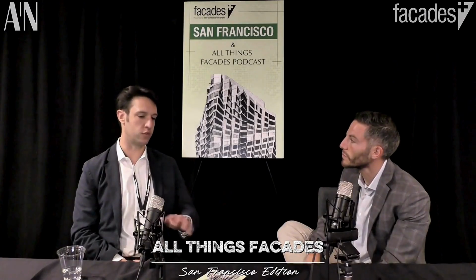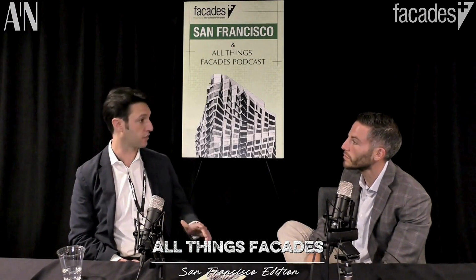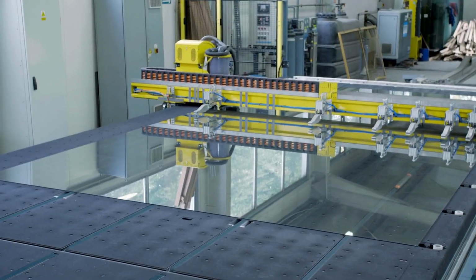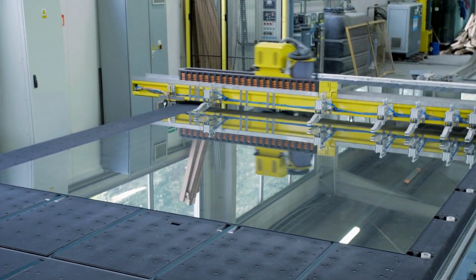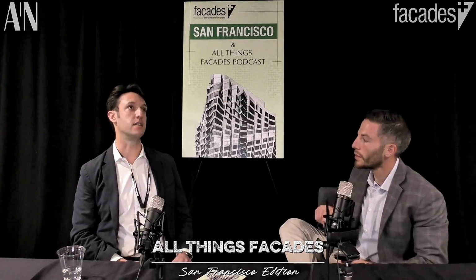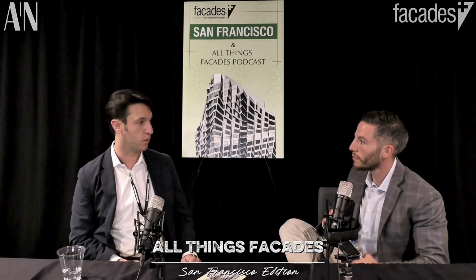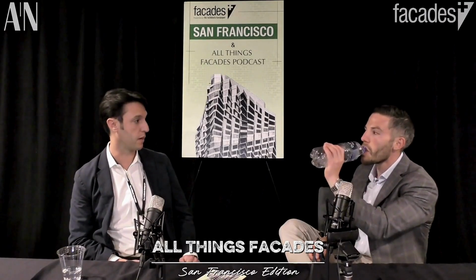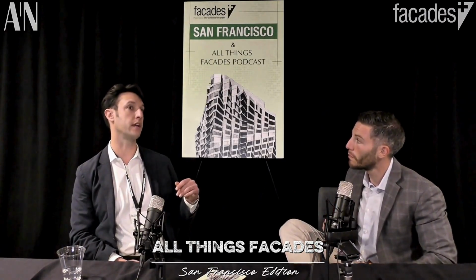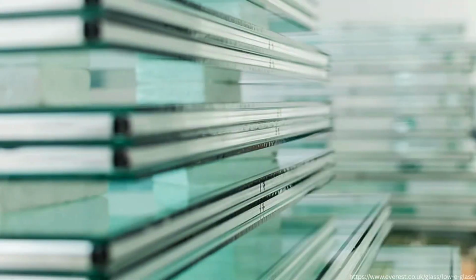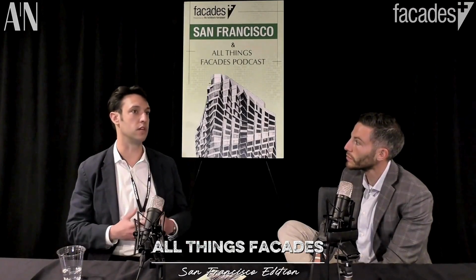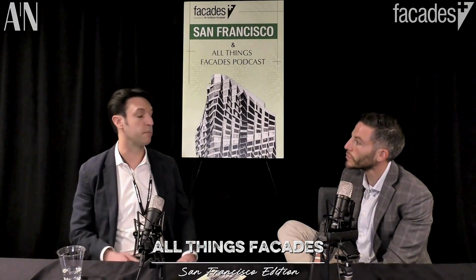Yeah, absolutely. Just one note: we are not a float glass supplier. We are actually bringing in float glass from float glass suppliers. The key differentiator with Viracon is that we are the only pre-temperable fabricator in North America. What that means is we bring in raw glass from those float suppliers, we then heat treat with uncoated glass, and then we add our low-E afterwards. That's a huge deal for flatness, and that's been a huge deal for a very long time.